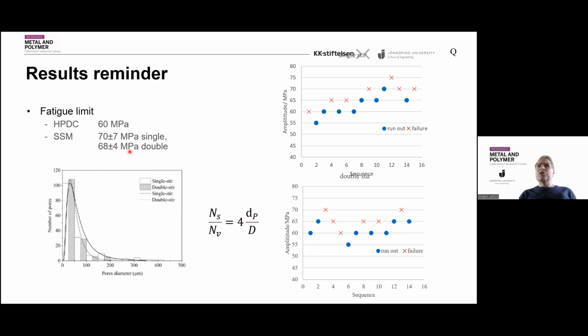And this is something which is still under debate for us, but it's definitely so that the defects here are not pore driven. So there are some other defects that we need to manage here, and this is where our research is continuing. When we looked at the pore size and the pore size distribution, we saw that we had a slightly reduced amount of the larger pores. So all the pores became smaller. But since it did not significantly affect in the semi-solid process, the reduced porosity did not significantly affect the fatigue life. There are other elements here that we need to look at.